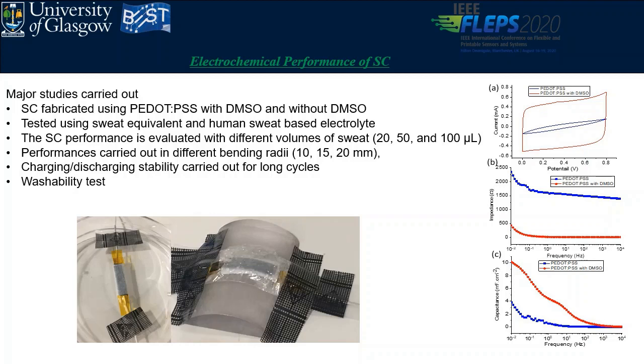For this work, we carried out different studies. Human sweat production may depend on the exercise or physiological status. So I tested different volumes of sweat, for example 20, 50 and 100 microliters, to see the influence on the supercapacitor. Also, during exercise there may be bending, so different bending cycles were carried out, and charge-discharge ability up to 6,000 cycles was measured. And of course, the last study I did was a washability test. I found washability has some issues, which may need to be overcome in future work. Here, in one of the images, you can see how the supercapacitor is attached on a curve. This is a small device for testing in bending studies.